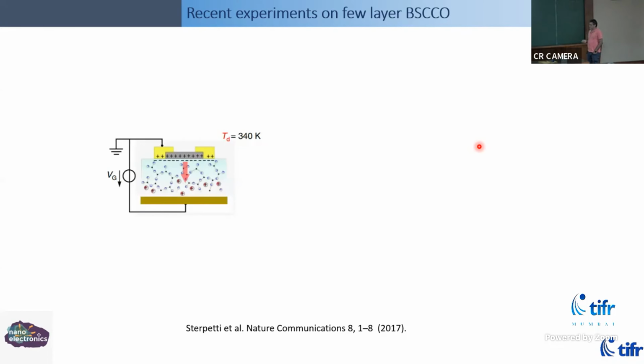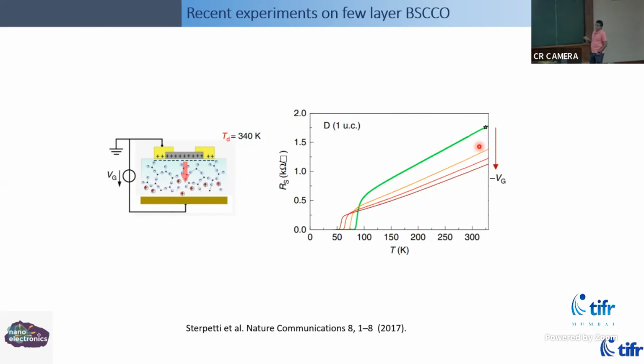People in the past used to do experiments on these kinds of materials by making many, many crystals of slightly different doping. These experiments with thin layers have allowed us to make a transistor-like geometry so that, in the same crystal, with the same disorder configuration, you tune the density. This is not our work, but we have done some similar experiments. You have the same device and you tune a gate electrode, which is a third electrode in a transistor geometry, and you dope it.